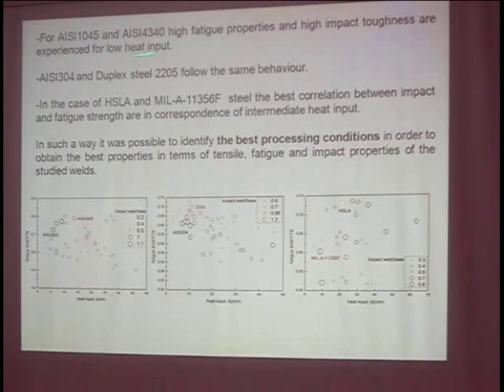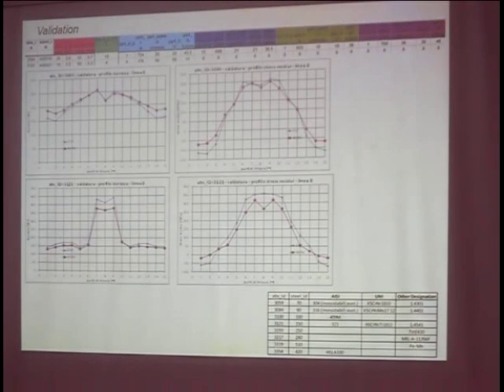We found that for AISI 1045 and AISI 4340, the fatigue properties and high impact toughness are experienced for low heat input. For 304 and duplex 2205, it is still the same behavior. For the high strength low alloy and MIL-A-11356F, the best correlation between impact and fatigue strengths is in correspondence of intermediate heat input, and in this way it was possible finally to identify the best processing conditions for the optimization of both mechanical and microstructural consequent evolution in our steel. This is some examples of the validation phase.